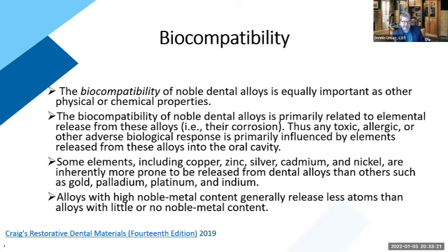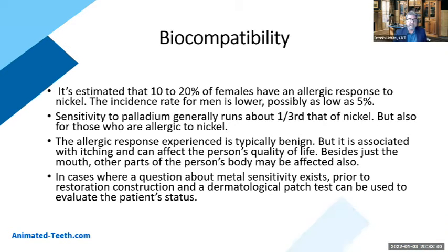They're inherently more prone to be released from these types of dental alloys than gold or palladium or platinum or indium. Alloys with high noble metal content generally release fewer atoms than those alloys with little noble metal content, like I just mentioned. It's estimated that about 10 to 20% of females have an allergic response to nickel, like I just mentioned, as far as when my mother got her crowns. And this incidence rate for men is lower, possibly as low as 5%. That's pretty interesting. So sensitivity to palladium generally runs about a third that of nickel.